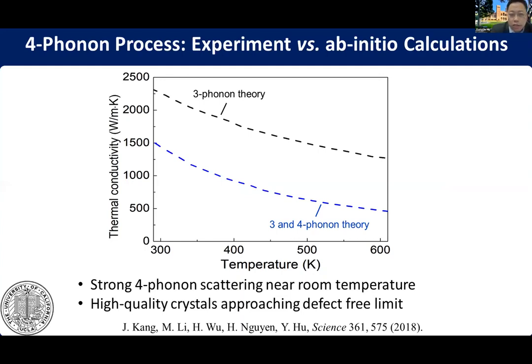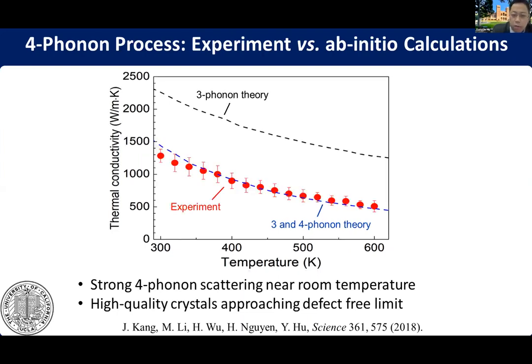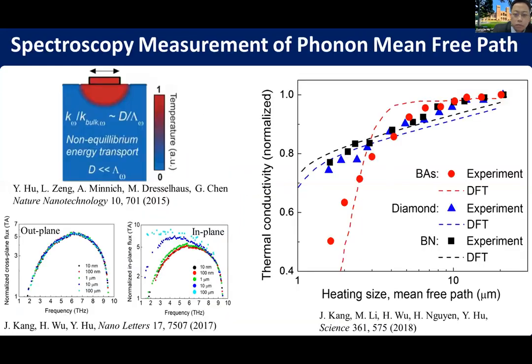So the black dashed line is a 3-phonon theory, and the blue dashed line is 3 and 4-phonon theory computed by Shengying's group and Lucas. So we did experimental measurement for boron arsenide from 300 to 600K plotted in the red symbols here. From this comparison, you can clearly see that experiment agrees very well with the 4-phonon theory. So this indicates that there is strong 4-phonon scattering near room temperature in boron arsenide, which however was negligible in most other materials. This also indicates the crystal has very high quality, almost defect free.